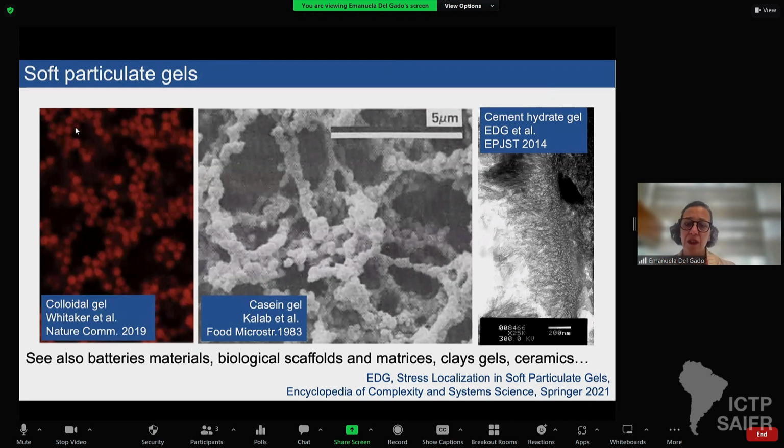One thing that is very interesting, intriguing, and annoying at the same time is that, differently from gels that we know more about, like biopolymer gels or polymer gels, where there is a more clear structure that we can then try to relate to the rheological properties, the structures in this type of materials, through this spontaneous self-assembly that can happen in very different conditions, can be very messy. It's very difficult to find common patterns, to see if there are self-similarities, and it's actually very difficult to predict the rheological properties from the structure. It seems even that there are no organizing principles in the end, that for each gel I have to think about it independently, as if it was a new material.